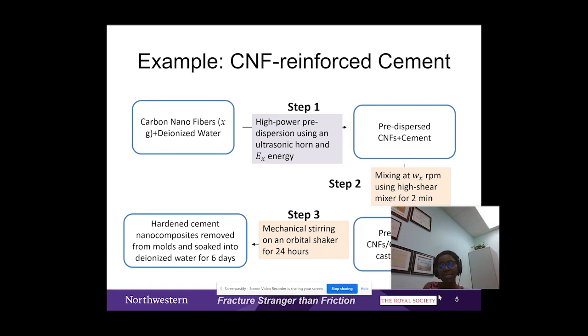So this is why in the second step, I'm going to be using high speed and high shear and cement powders. This time the unhydrated cement grains are going to help me further disperse the carbon nanofibers. And then after pouring the slurry, I'm going to be using an orbital shaker. And with mechanical stirring, I will keep breaking any potential clusters of carbon nanofibers so that I obtain at the end a uniform and well-mixed carbon nanofiber cement composite.